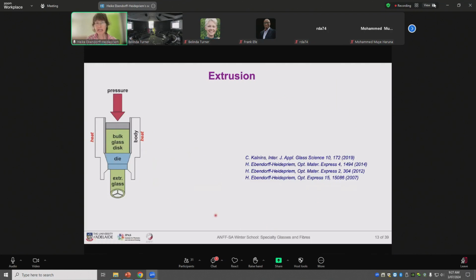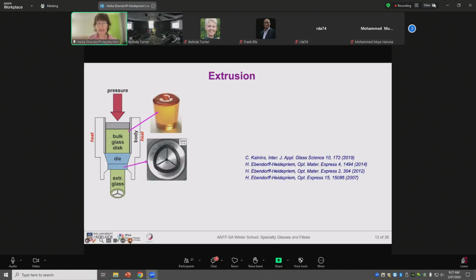Another technology is extrusion. For example, you make a solid glass billet, place it on top of a metallic structure, a so-called extrusion die, and then heat up the glass and die, and then squeeze the glass through. Where there is a pin that blocks the glass flow, there is then a hole in the extruded preform. So the extruded preform always has the inverse structure of the metal die.